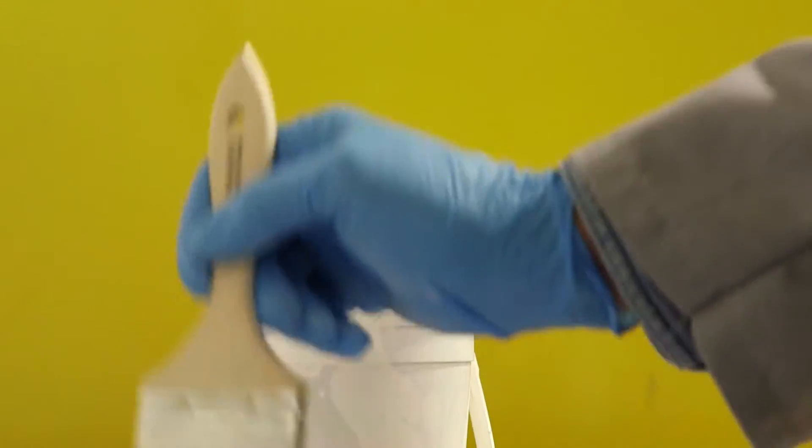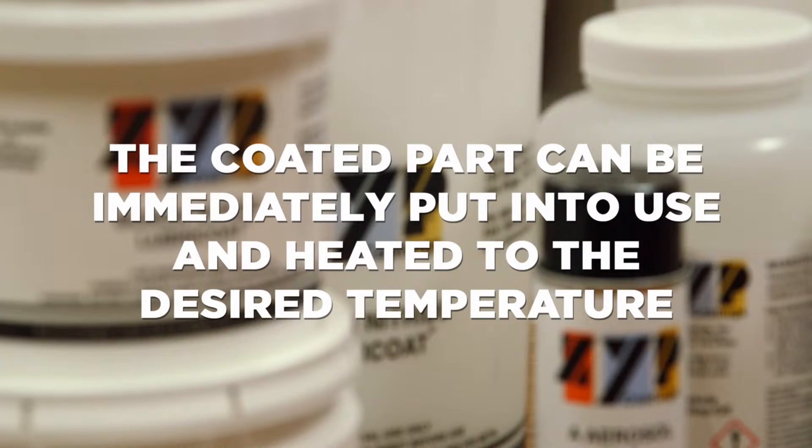Even so, the thicker the coating, the greater the likelihood of some amount of delamination, peeling, or flaking on cool down from the used temperature. The dried and coated ceramic part can be immediately put into a furnace.